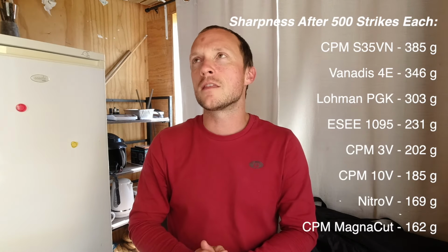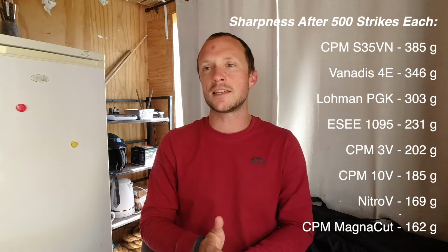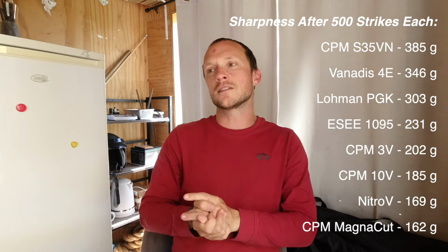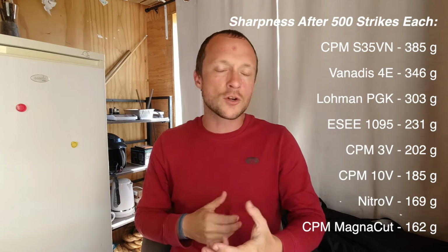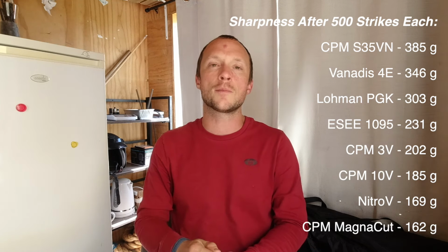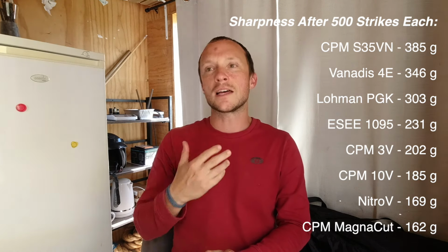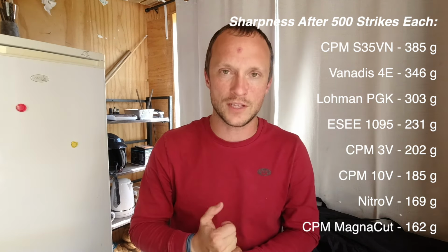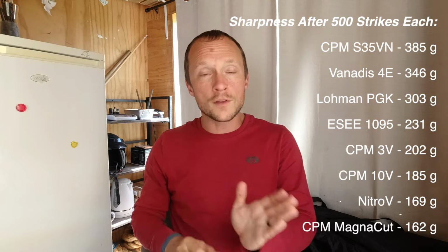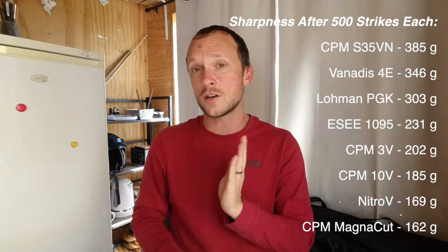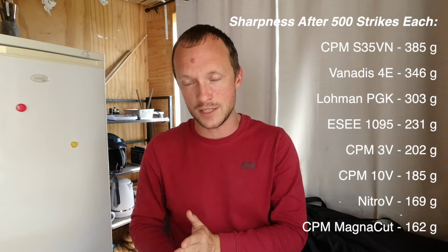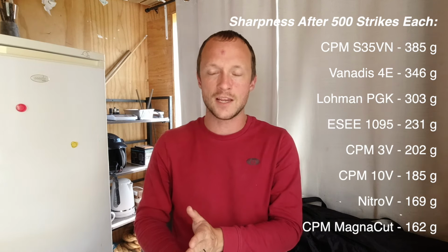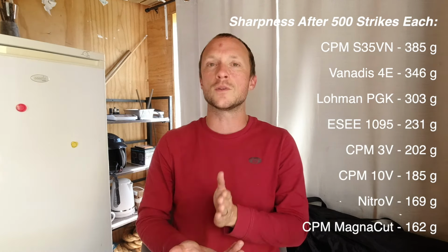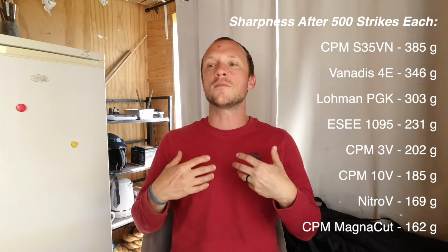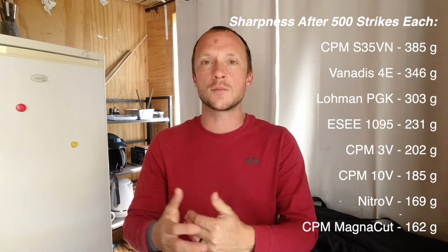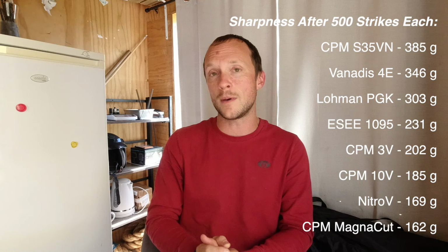Now, you should note that the edges were not all sharpened exactly the same. I've found good results on steels that are low vanadium with my traditional water stones, my aluminum oxide stones, and stropping with Mother's Mag and Aluminum polish. So that's what I did for all of the steels that have less than 3% vanadium. All of the steels that have more than 3% vanadium, and therefore very, very hard carbides, I sharpened on diamond and stropped on diamond to try to give them the best possible chance of having the toughest edge possible, because their carbides would not have been cracked or shattered or mashed, but would have been cut cleanly with progressively finer diamonds down to 0.25 micron strop.